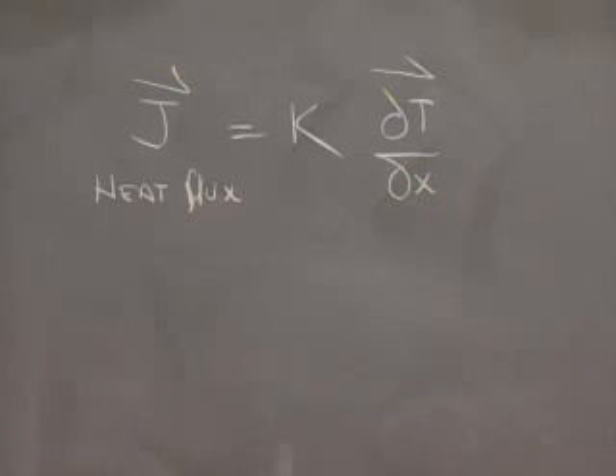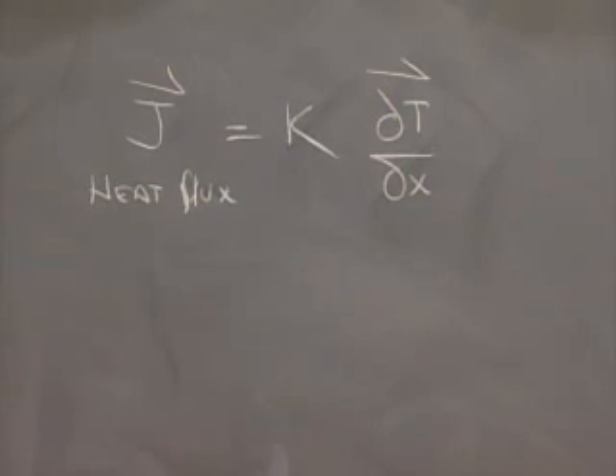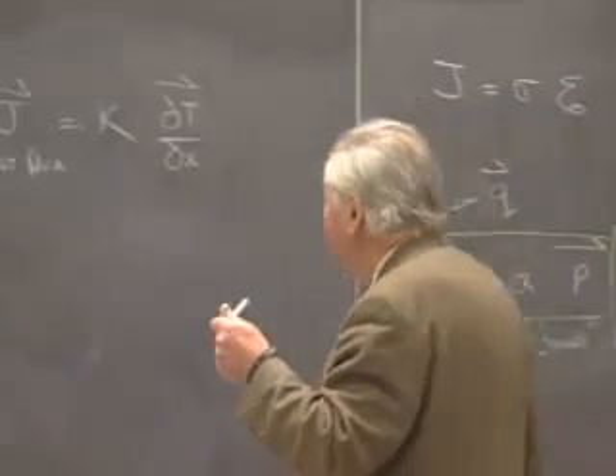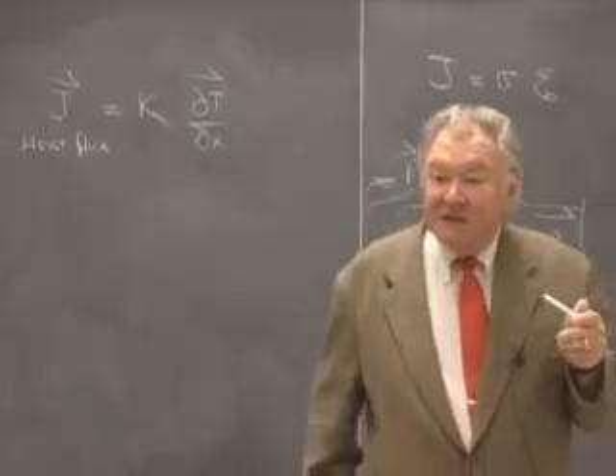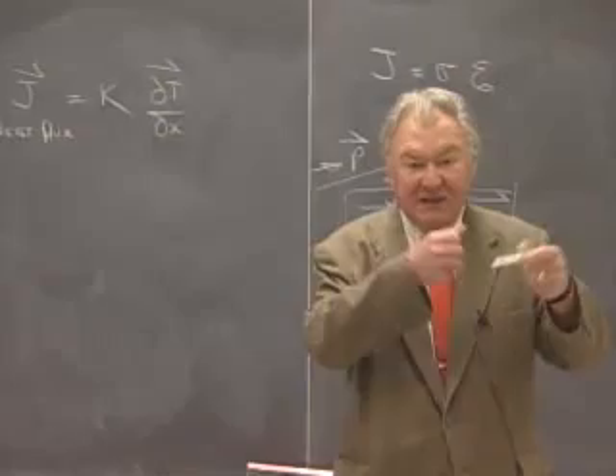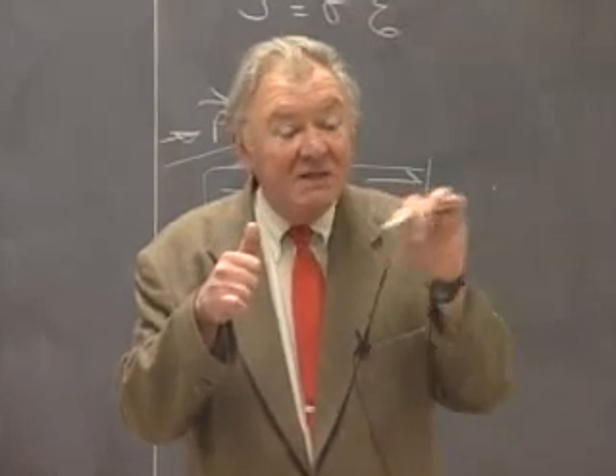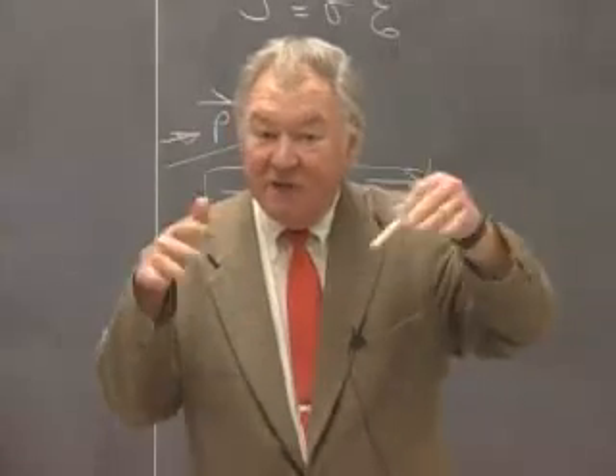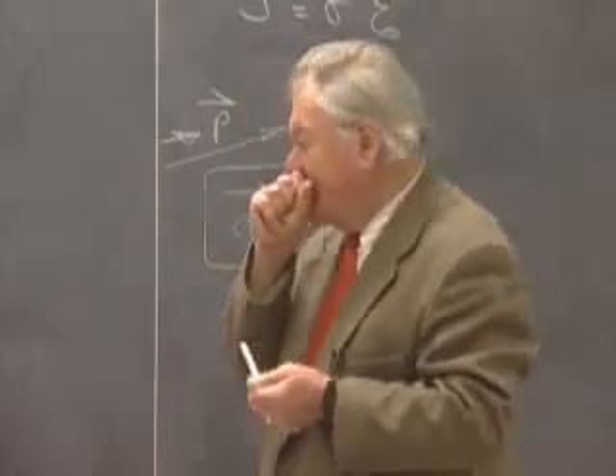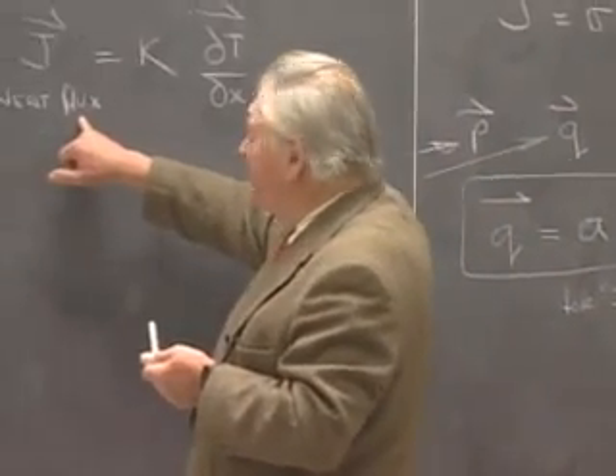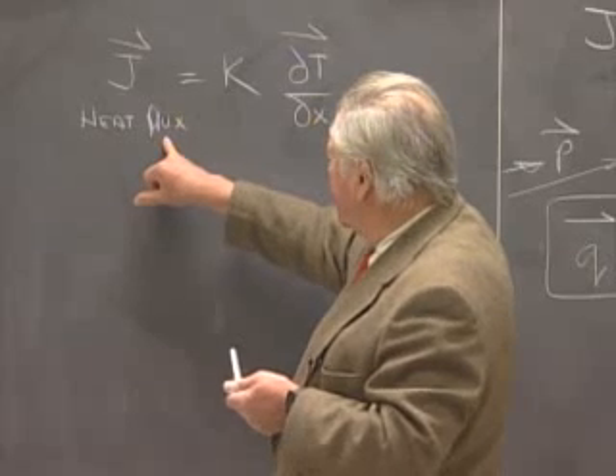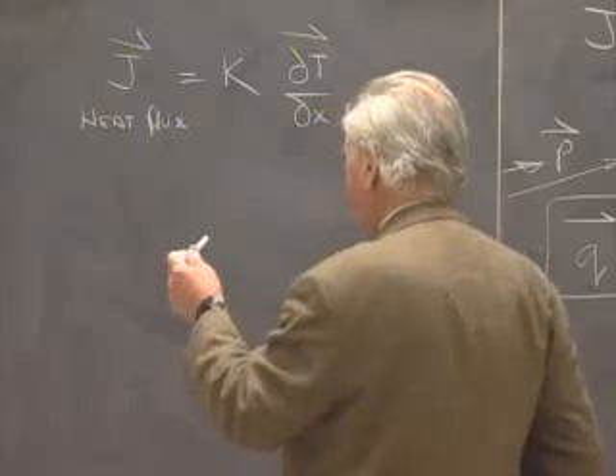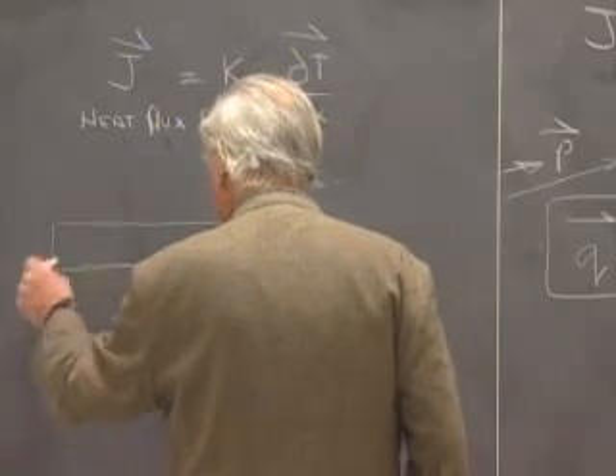The thing that gives rise to thermal conductivity can be either propagation of radiation, like as in propagation of light traveling through a transparent material, but the other mechanism for thermal conductivity is modes of lattice vibration. When a material is hot, the atoms are jiggling around, and you can make the displacement of an individual atom be represented by a sum of waves moving in all different directions with a variety of wavelengths and a variety of amplitudes. Take all those waves, add them together at a particular time, and you get the displacement of the atom. Propagation of heat by this mechanism, by modes of thermal vibration, can be very, very anisotropic. And probably the best example of this is get a single crystal of graphite.